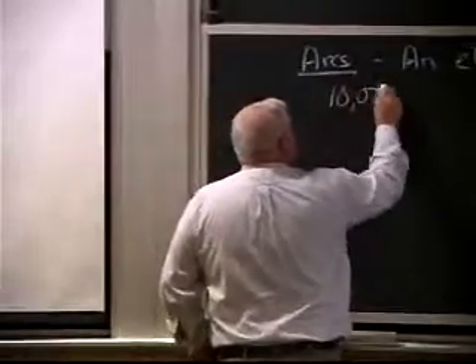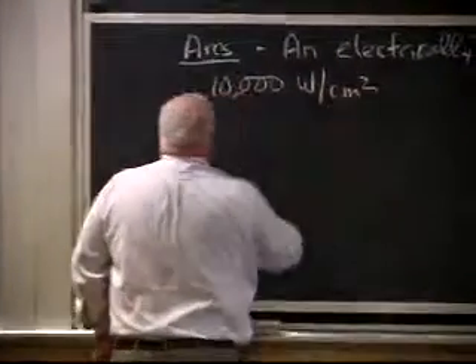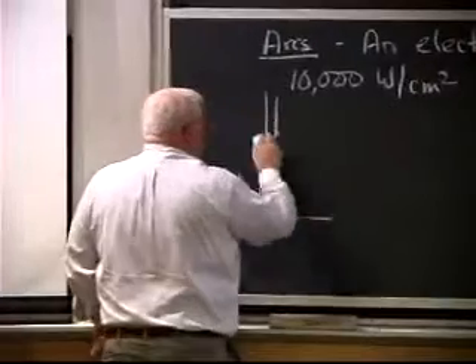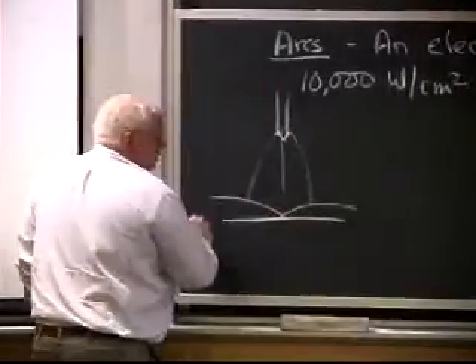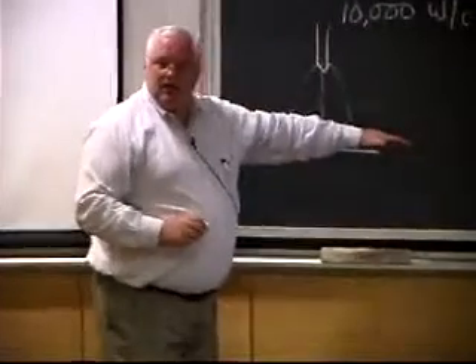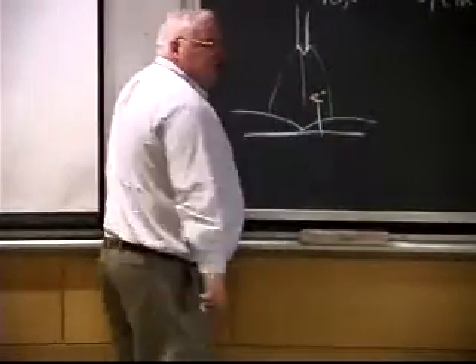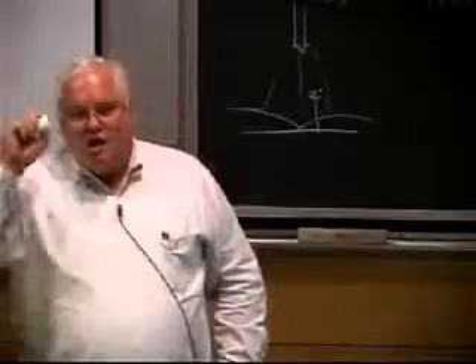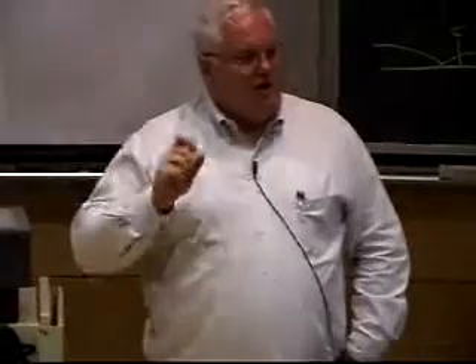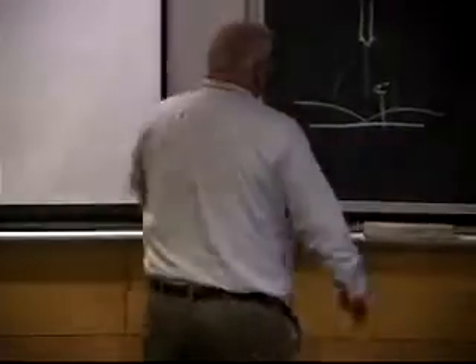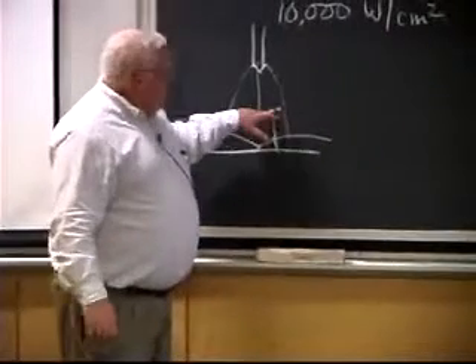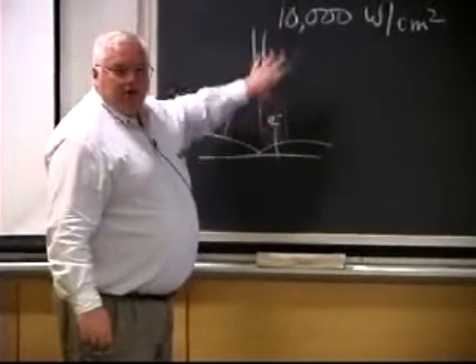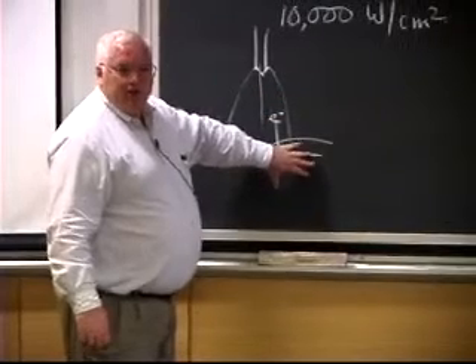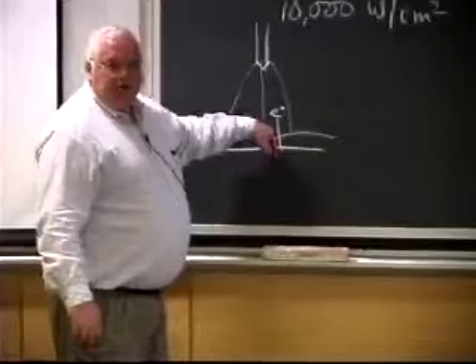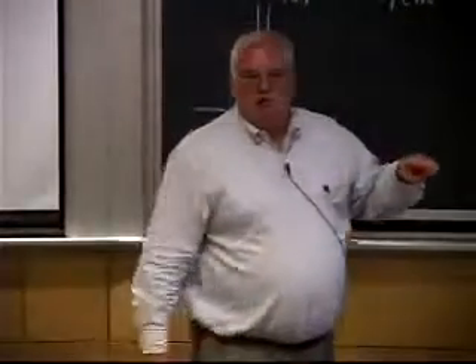With an arc, I can get 10,000 watts per square centimeter. And the reason is, with an electric arc, I've got an electrode up here, I've got a surface here, and I have these electrons flowing. I actually have a boundary layer. I have the gas coming in, and I have the gas going across. But the thing that's neat about an arc is the electrons punch right through it. And it turns out that, I'm going to show you later, 90% of the heat is carried by the electrons in an arc. So if the boundary layer is limited to 1,000 watts per square centimeter, but I can get 90% of my heat by this, I can get 10,000 watts per square centimeter, because 9,000 comes from the electrons and 1,000 across the gas boundary layer. And so what I've done with an arc, by applying electric current, I'm using electrons, because they're smaller than ions, to punch through the boundary layers.